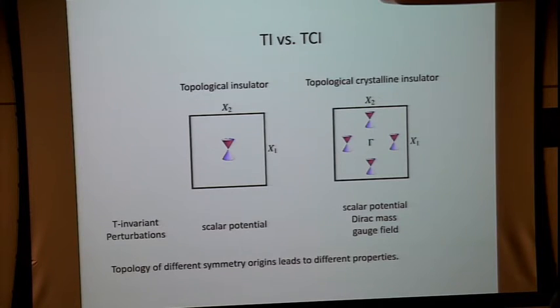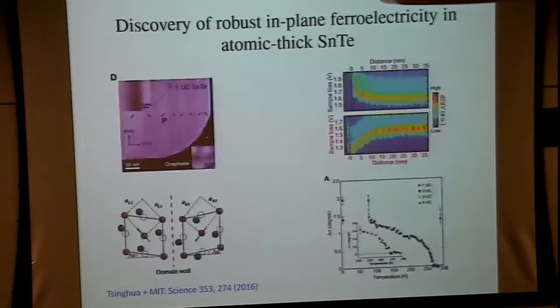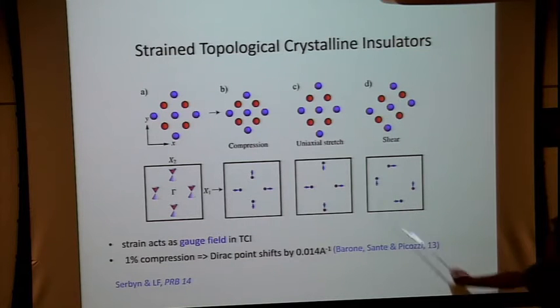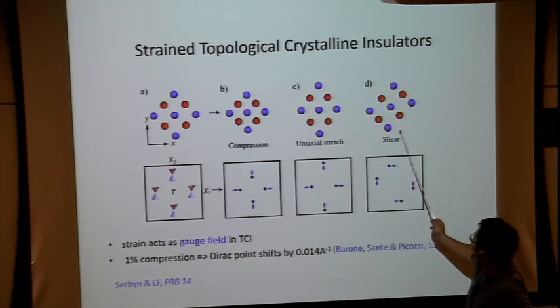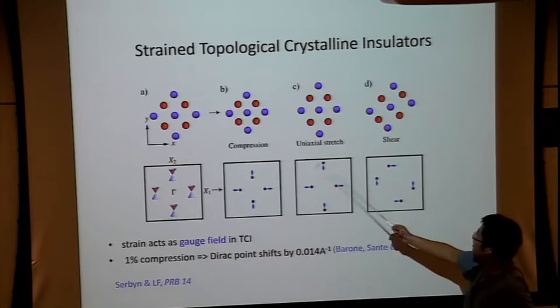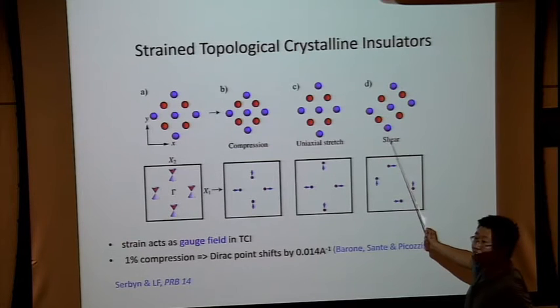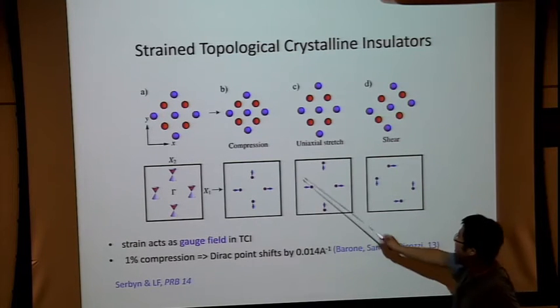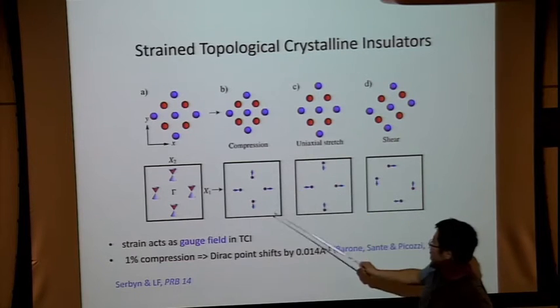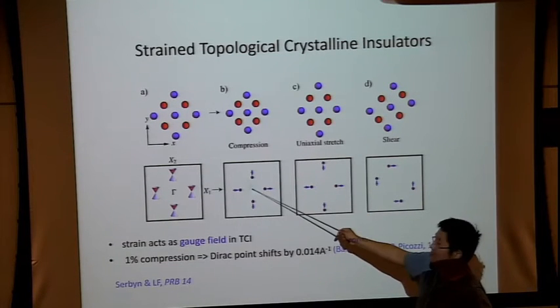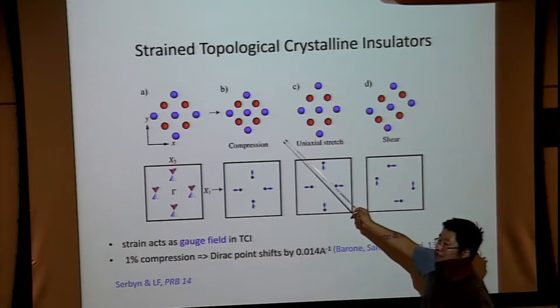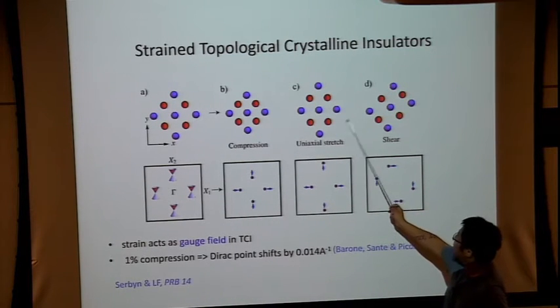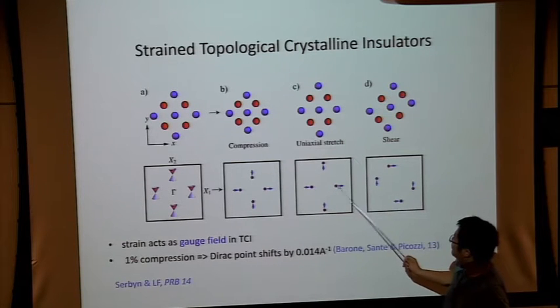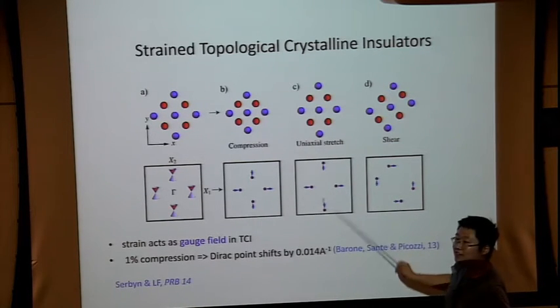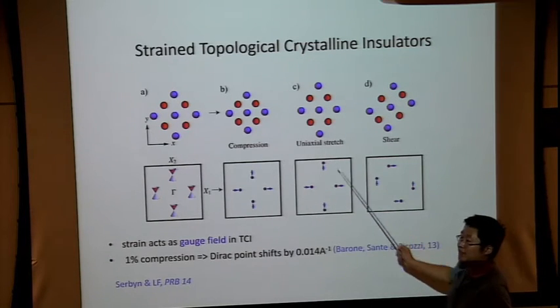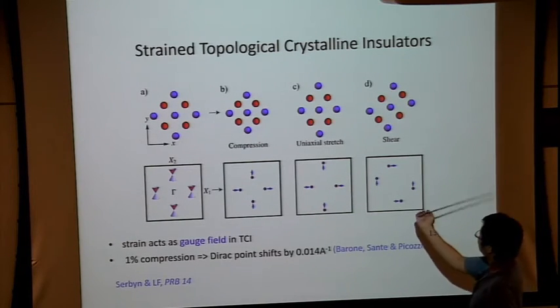Okay, since you're asking, let me maybe just move on. I probably won't have time to talk about it. But this is what I mean. Does this help? Shear, stretch, and compression all contribute gauge field. For example, if I have a compression which preserves the rotation symmetry, all Dirac points shift identically towards the center, because the rotation symmetry is preserved. But uniaxial stretch makes the x and y directions different. So in the x direction, they shift towards the center. In the y direction, they move towards the edge. And this is shear. In shear, basically you rotate the whole axis.